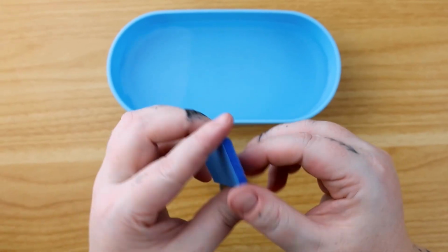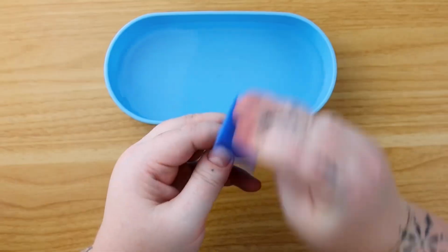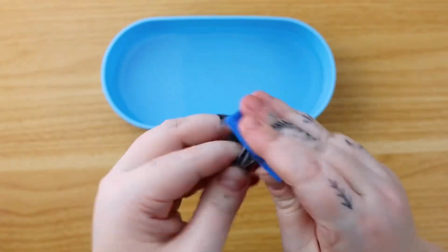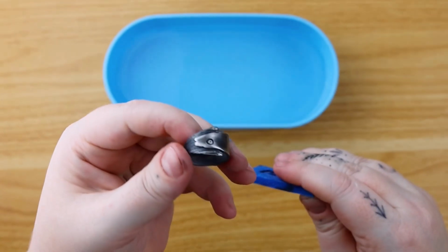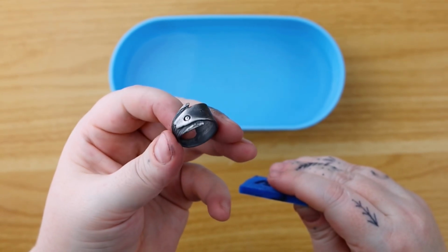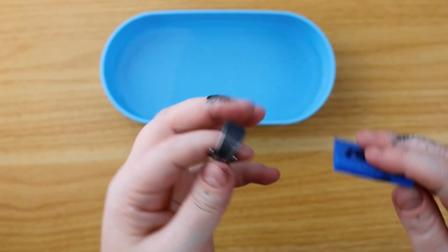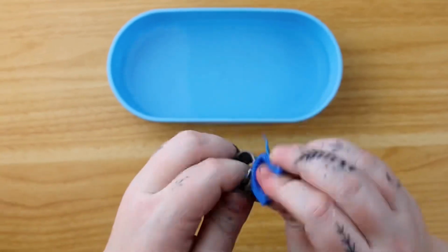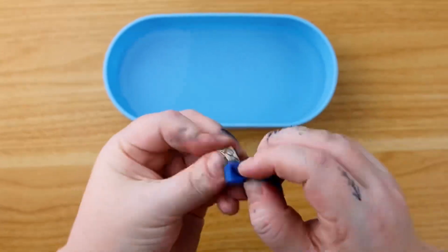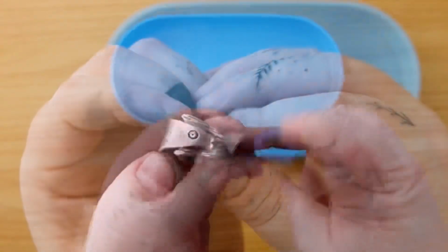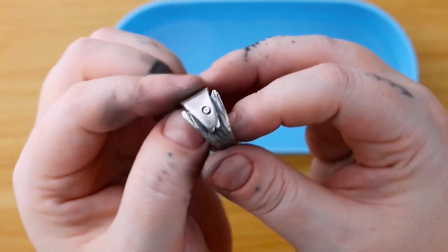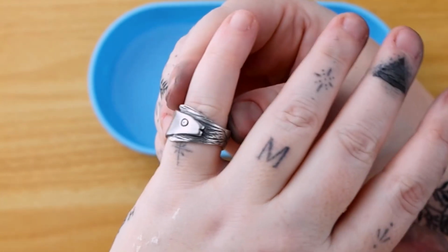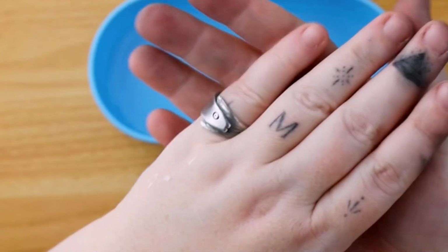Now to achieve my weathered look, I'm taking the 1500 grit and I'm going to add some water. And I'm brushing back the top of the patina. Here you can see it has only removed the top layer of patina. This brings out the raised silver details while keeping the dark tones in the textured areas. You can see a dramatic change almost instantly. I will continue this method until I'm happy with the look that I'm going for.